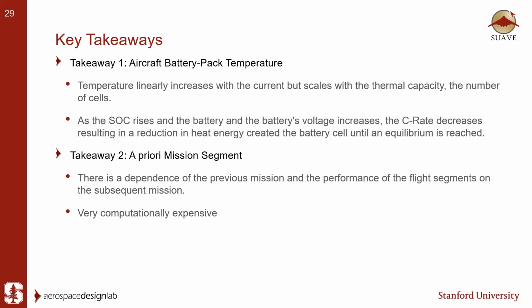Now, during charging, on the other hand, when the initial state of charge is low, the relationships previously mentioned predict high internal resistances, resulting physically in an initial stark increase in temperature. As the temperature increases, the diffusion of ions increases, the internal resistances drop, resulting in less thermal heat being created. And this can be seen as the voltage increases, the current or the C rate decreases, and as a result, the temperature starts to attenuate.